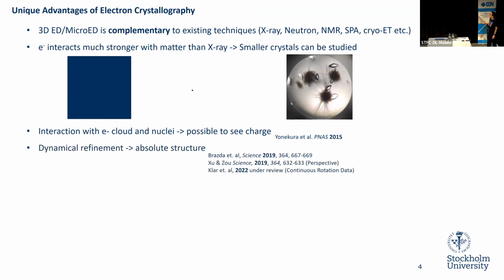We also have the dynamical effect. You heard there are a lot of errors in X-ray diffraction; I think in electron diffraction we have even more errors, and one of those is the dynamical effect, which is due to the strong interaction between electrons and the crystal. Electrons can get scattered multiple times going through a crystal, so the intensities we measure become really inaccurate compared to X-ray. But now there are a lot of efforts being put into modeling this dynamical effect, and by doing this, we can actually get more information from the crystal.